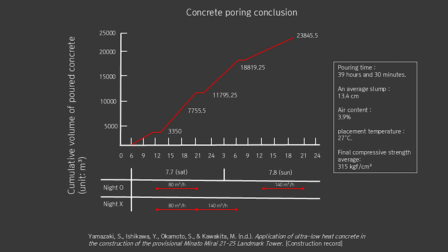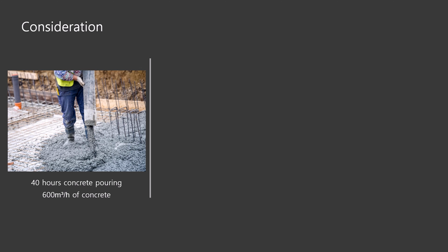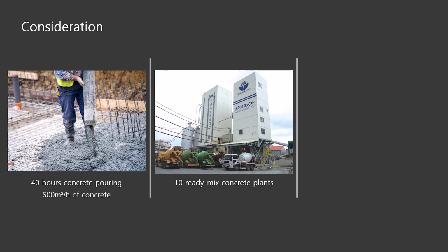The average slump was 13.4 centimeters, air content 3.9%, and placement temperature 27 degrees. Final compressive strength averaged 315 kgf per square centimeter, exceeding expectations. In the heart of the city, non-stop concrete pouring for 40 hours was a monumental task. We had to supply 600 cubic meters of concrete every hour. 10 ready-mix plants within 40 minutes were selected. 5 of them could operate through the night.